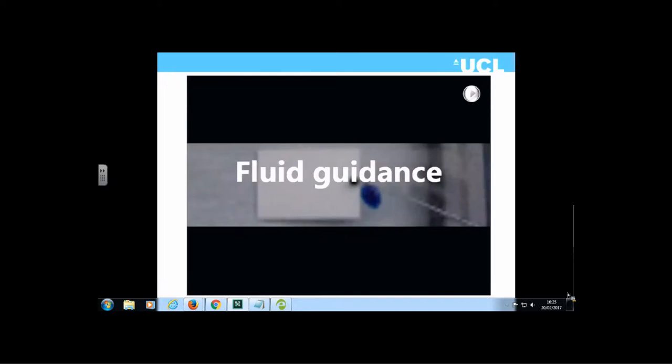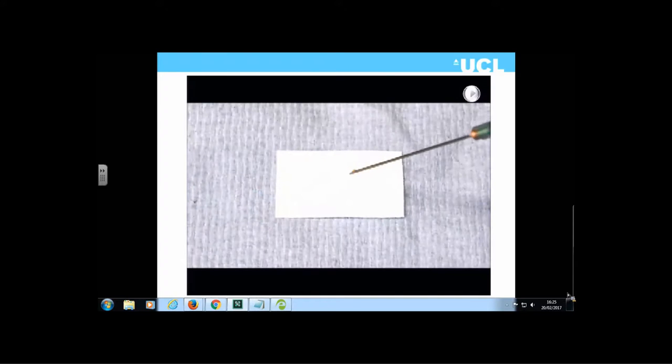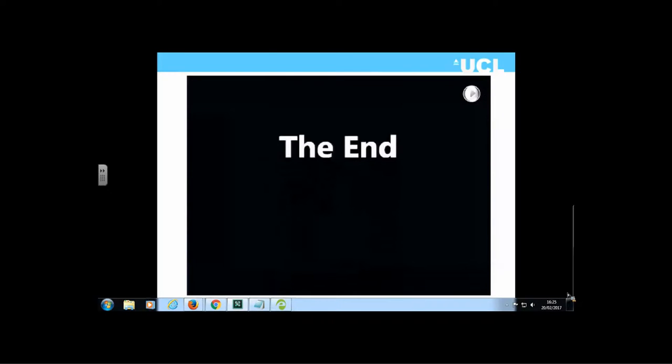The surfaces can also be used for fluid guidance. The surface is largely superhydrophobic, but by using a UV mask system, a pattern is created on the surface so that water can travel in predetermined directions. Systems have also been developed where water can be raised upward — similar to what plants do — using capillary action, raising water by about four to five centimetres. The result is distinct patterns where water wets some parts but not others, allowing flow in specific channels.